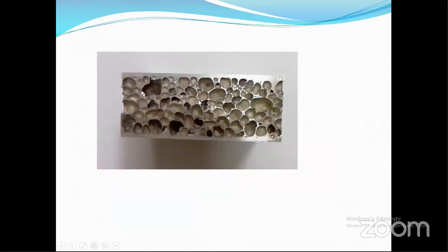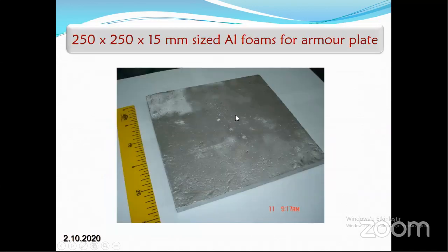This is the sandwich structure. This is also the cross-sectional area of the sandwich structure. That's quite good, actually. This is a very big sample, 250, and the thickness is 15 millimeters, aluminum foam. This is for armor plate.